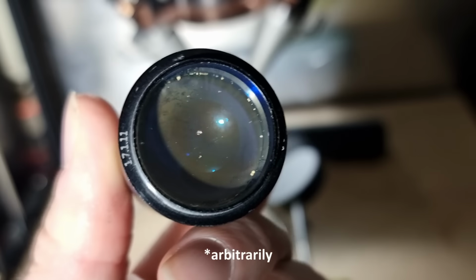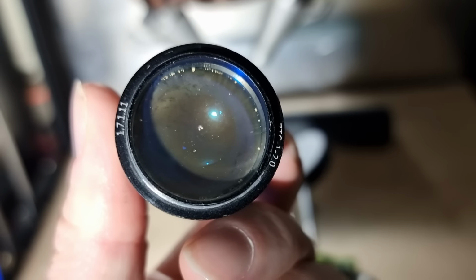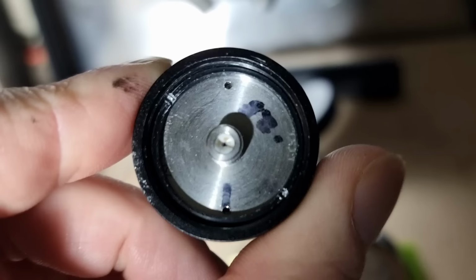It could have been that my layer height increments needed to change, or it could have been that the accumulation of heat was broadening the profile, creating a sagging effect. Either way, it wasn't good news. I was reluctant to start changing parameters at this point as I had already blown a couple of fibres, each time costing me a couple of days and several centimetres in fibre length.